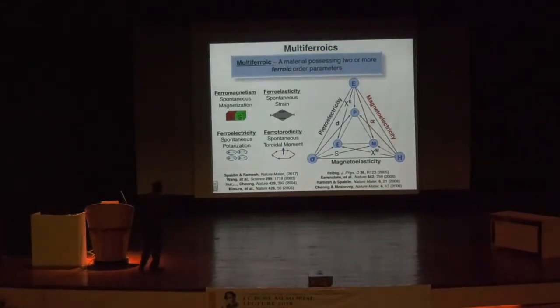So these are materials, and here's the description of order parameters. Ferromagnetism breaks time symmetry. It's got a spontaneous magnetic moment. Ferroelasticity is martensite, for example. It neither breaks time symmetry nor spatial inversion symmetry. A ferroelectric or a piezoelectric breaks spatial inversion symmetry, but it doesn't break time symmetry. Ferrotoroidic materials break both. And bismuth ferrite is one of them. We're going to talk about it.